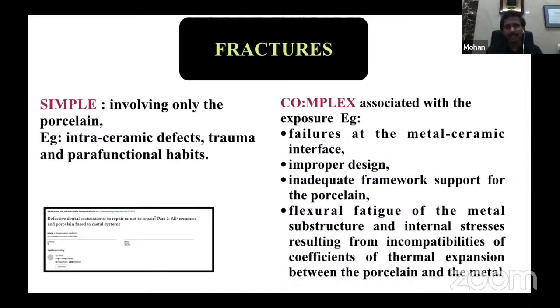So coming on to the fractures, that can be simple or complex. Probably this article was written related to the porcelain fused to metal, but it also applies to the layering technique. If you do not want layering, then we do the staining technique. That's what I wanted to tell you. So in layering technique, it's simple if the underlying substrate is not visible, and it is complex if the underlying substrate is exposed. So in a PFM, if the underlying metal is exposed, then it becomes complex. Otherwise, it's very, very simple. What you have to do is give a bevel and then put the composite and then do an intraoral repair.